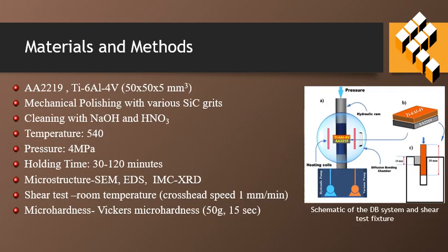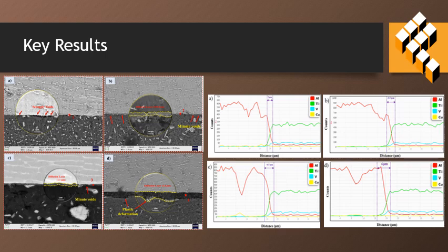These are the materials and methods which are incorporated in the current study. BSE images of the diffusion welded joints produced at 30 to 120 minutes are shown here. Many scraggly voids are observed on the interface when the holding time was 30 minutes. However, the IMC layer is observed when the holding time increased to 60 minutes and more, with the elimination of irregular voids. When the bonding time increased to 120 minutes, the plastic deformation of the interface is observed.